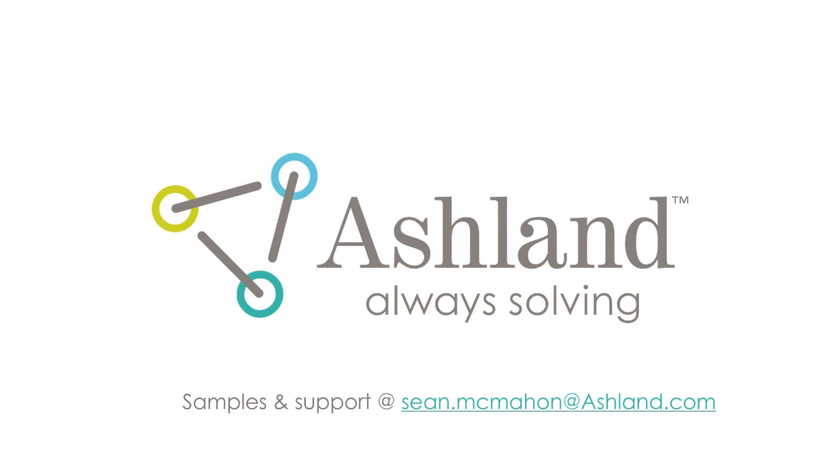Our next question is, how are PLGA-based formulations sterilized for pharmaceutical use? Are there any side effects that we should be concerned with? Yes, and again, really good question. There certainly are side effects that you should be concerned with depending on the method that you use. I mentioned earlier that there are about 13 options that you come across when you read about this. If you like, we could go through the 13 options and talk about the ones that are relevant, but of those, 4 relevant options are irradiation techniques, so gamma irradiation or electron beam irradiation, which are quite commonly used, ethylene oxide, which is often used, or sterile filtration. Those are the 4 options that I would suggest considering if it's possible to use them.